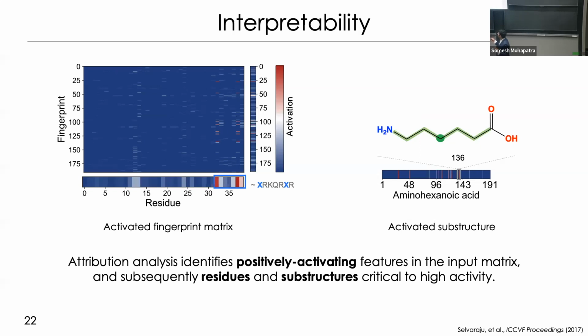And by averaging across these fingerprint indices, we looked at the residues or the motifs which were more critical to the model. Anything that has a high activation is essentially contributing more to the MFI or the activity for that particular peptide. So we looked at one of these particular amino acids or residues, X, which is an unnatural residue, aminohexanoic acid, and just looking at its entire structure, we could go back and find what substructure matters more to it. And the substructure was the alkyl backbone in this case.